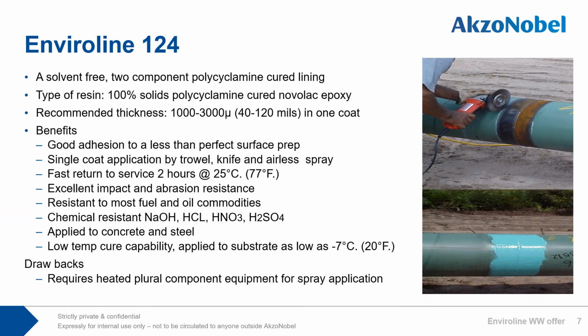We will begin with Enviroline 124, with origins going back 60 years as a quick-set epoxy to adhere to the steel cover and closing up of an existing underground oil storage tank after lining the interior and making it ready for a quick burial. It is a solvent-free 2-component polycyclamine cured Novolac epoxy and is highly viscous, can be applied at 1,000 to 3,000 microns in a single coat.